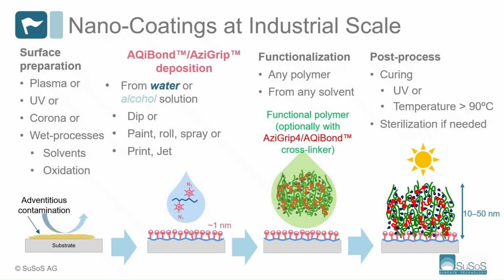Then we can functionalize by depositing any other polymer from any solvent, be it inorganic or organic solvent. And we post-process it by curing, as I said, with UV, or as it is for the first class of AQiBond polymers, using temperature. This temperature is above 90 degrees Celsius. And such a sample can also be sterilized if needed.